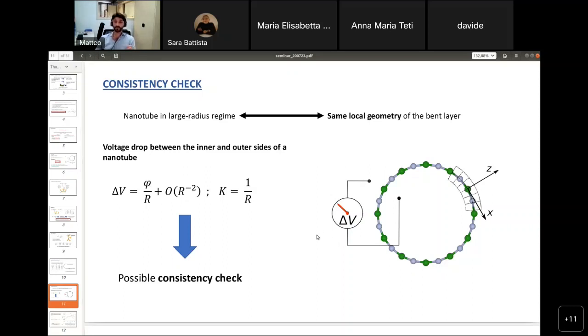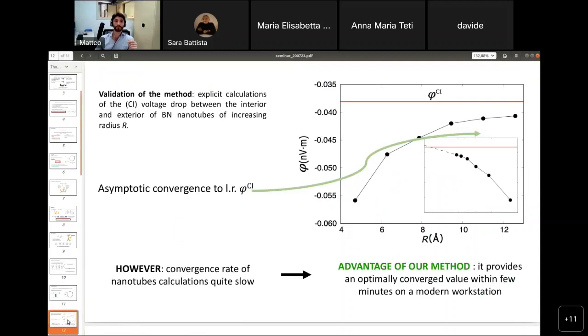Indeed, it is well known that the voltage drop between the inner and outer sides of a nanotube is given by the expression that you can see here, where R is the radius describing the nanotube, and its inverse is the curvature describing the cylindrical geometry of the tube. Then the constant of proportionality between the voltage drop between the two sides and the curvature has to be the quantity that we defined and that we calculated. So nicely, such a system provides a possible consistent check to benchmark our method and then the validity of our results.